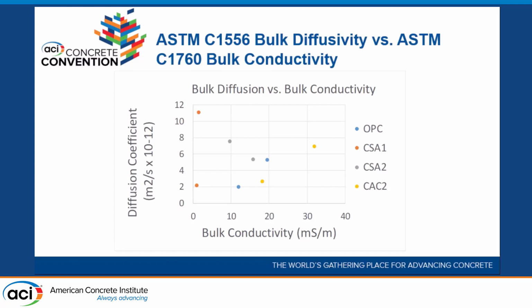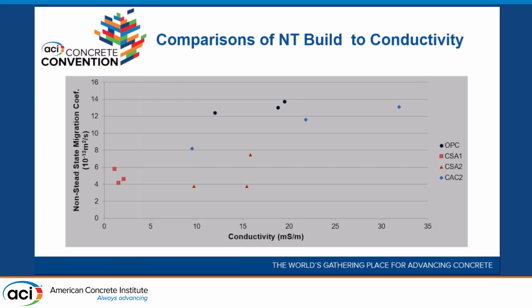That, of course, would be related to the formation factors and some other things. So you can see down the road, you've got a couple of things that have the same, let's say, 2 times 10 to the minus 12 on the bottom, but there's a fair range of where the conductivities are. So for a given material, you can get the conductivity relationship to the bulk diffusion, but it isn't the same relationship for any other material. The same thing if we did NT Build with conductivity, same general idea. The NT Build numbers go up when the conductivity goes up, but once again, for a given material, the conductivity and the bulk diffusion have a more known relationship. And so we should keep that in mind.